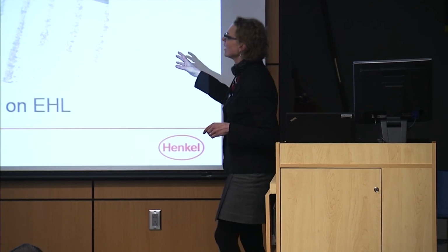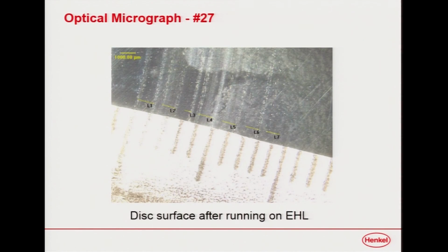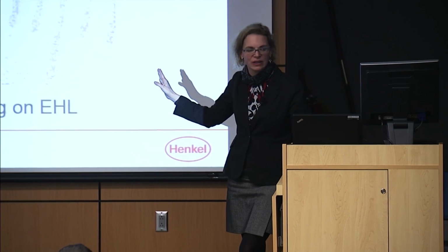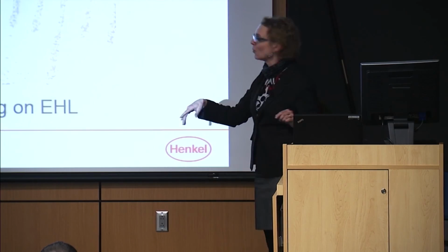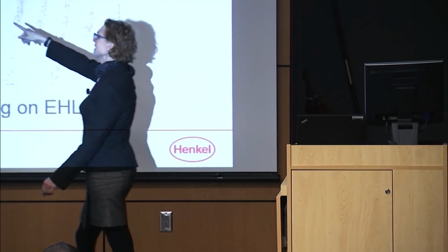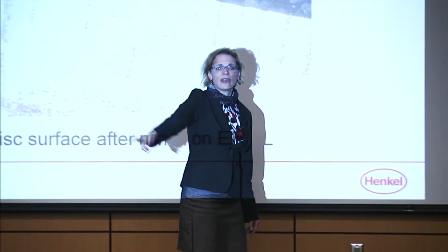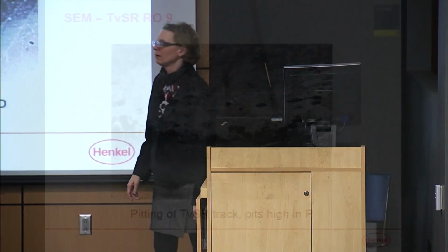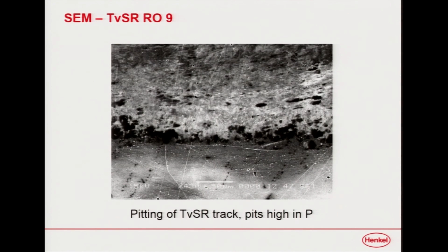And then we started even going on to optical micrography. If you look, you can actually see where we ran. You can see that there's changes in the surface. Well, these are for various materials, and the more active, the more polar or even covalently active they are, the more things change, to the point that we got this. When you throw that surface into the SEM, you get holes in it.